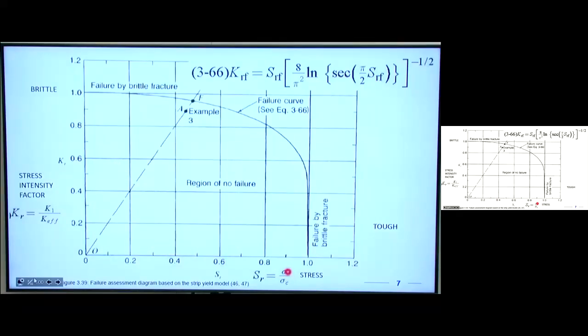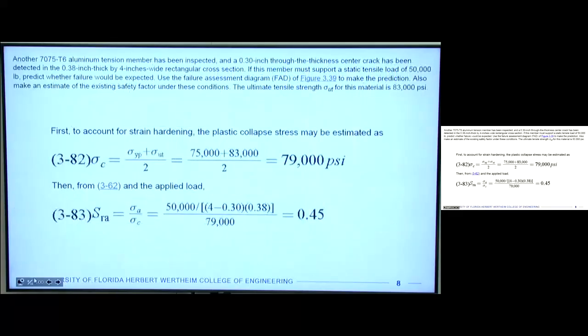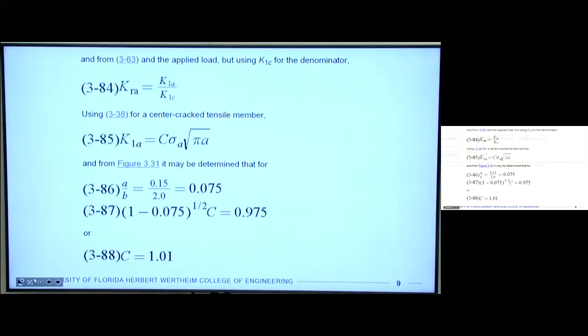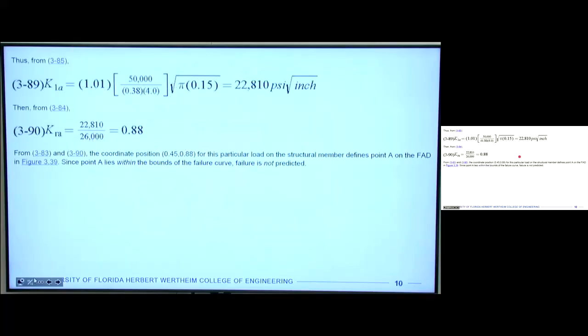But you're always going to have some applied stress, so you can never be at the origin along the x-axis. But you may, in fact, get a brittle fracture if you have a low applied stress compared to the collapse stress, like maybe even 0.1, if your KR is really high. And so you can go back and think about how this could be a design problem. If this KR is very high, like if the value we calculated for our fracture toughness gets close to the K1C, then this value would go very high and it would get close to a brittle fracture, even with very low loads applied. So it's kind of a balance between these two things that we're looking at today.